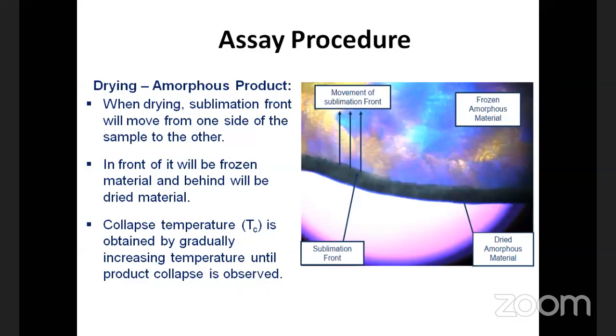are different ramps. We have to slowly, stepwise increase the temperature by a degree or 2 or 5 or 10. Usually a 2-degree ramp is used, but it depends upon the type of material and the amount of material. So collapse temperature is obtained by gradually increasing temperature until collapse is observed. So we have to keep on increasing the temperature, moving towards 0 degrees Celsius. And at one stage you will find that the material is not drying, but it becomes soft and the structure is getting collapsed. So that change you can observe here in this particular region.